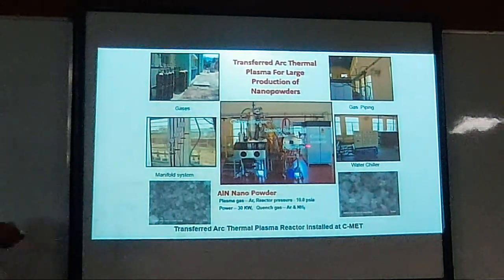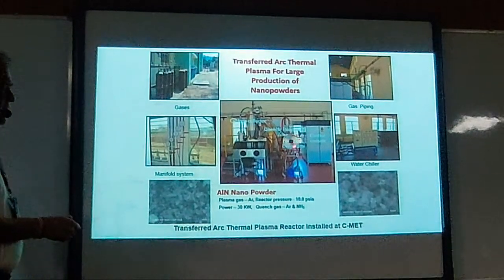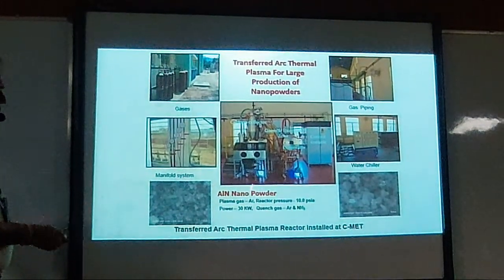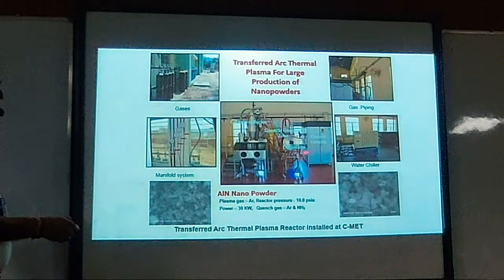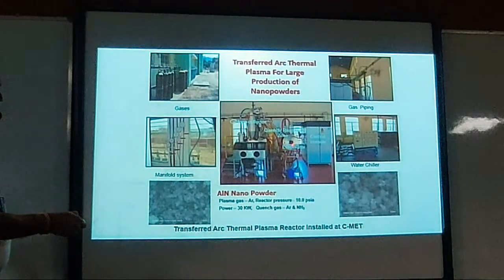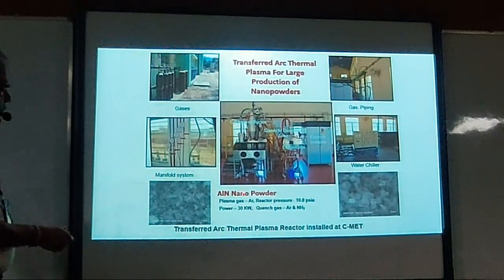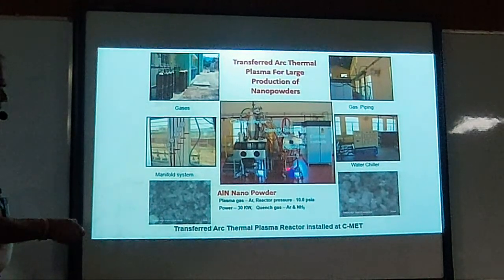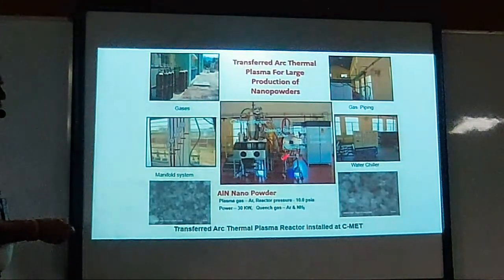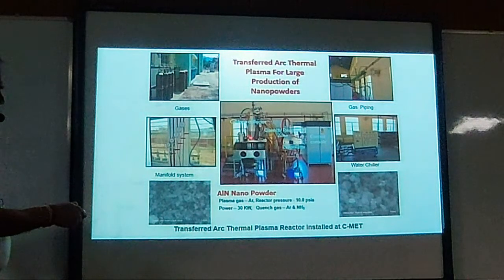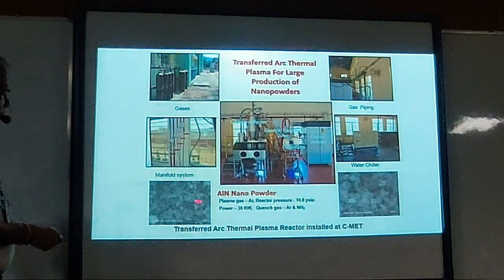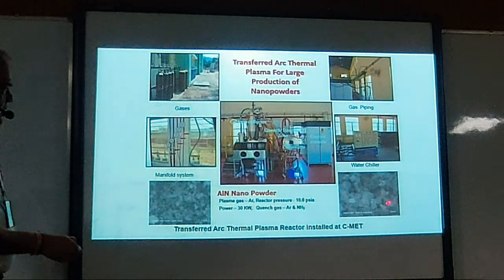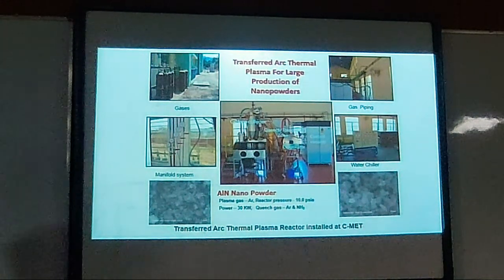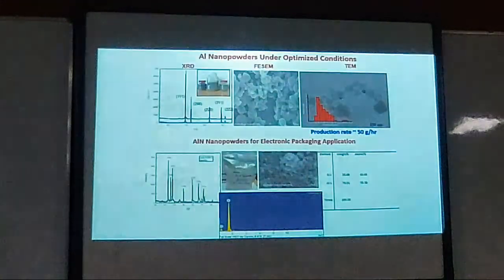What is the plasma reactor? This is a plasma actually. So your material itself works as a cathode, and the temperature goes to 3000 degrees centigrade. This aluminum gets vaporized, and then we can add nitrogen and ammonia along with that and quench this aluminum nitride powder in this glove box. So we get a very fine 50 to 100 nanometer scale powder.